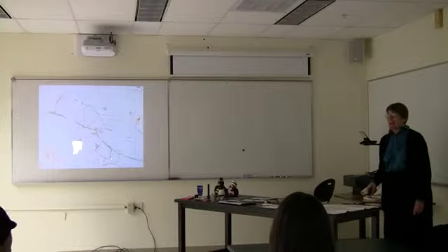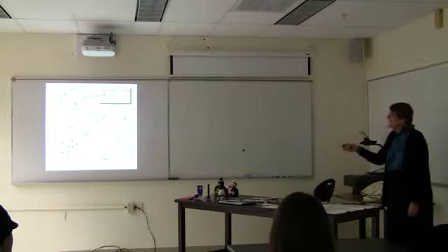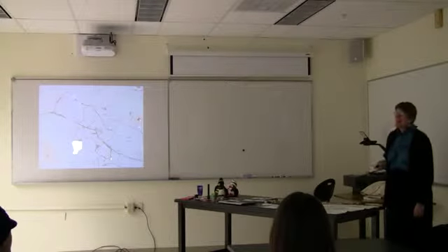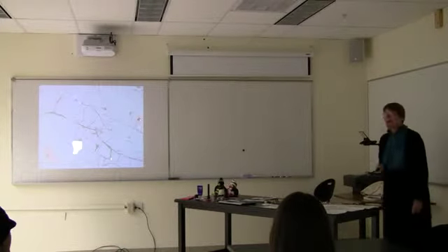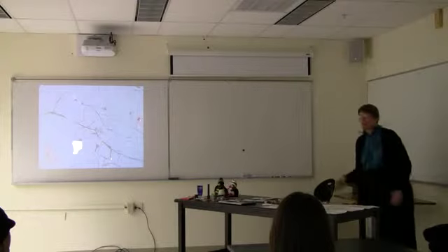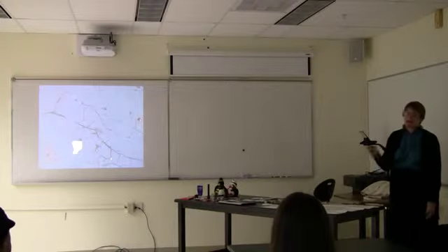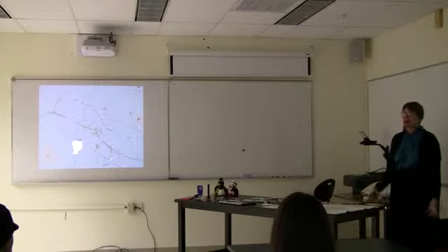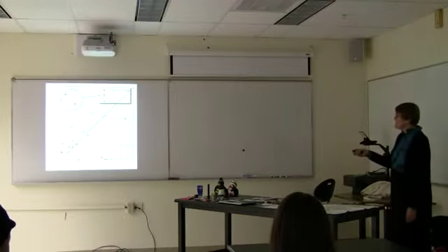And I immediately wrote and said, well, these have all this oldhamite, and some of them have a significant amount of oldhamite, up to maybe 2%, which is the number they're talking about, and your oldhamite is weathered away. So your porosity is going to be higher than expected because you've lost a mineral grain.